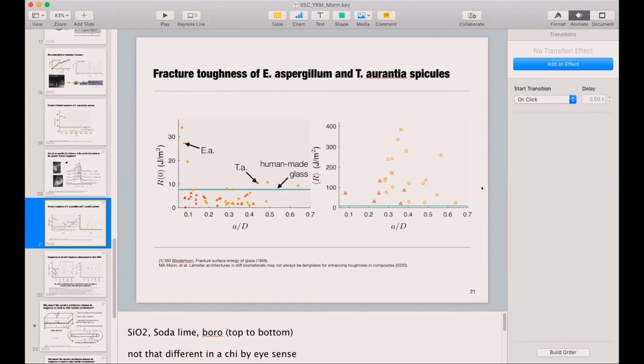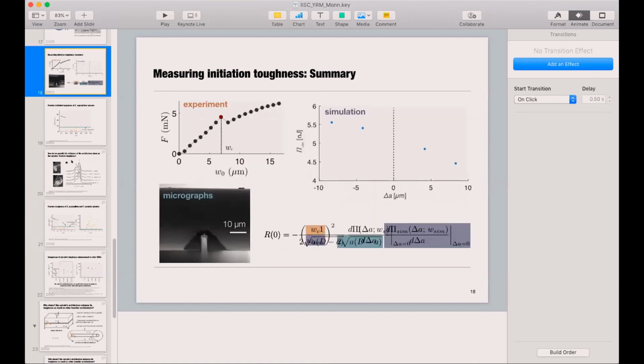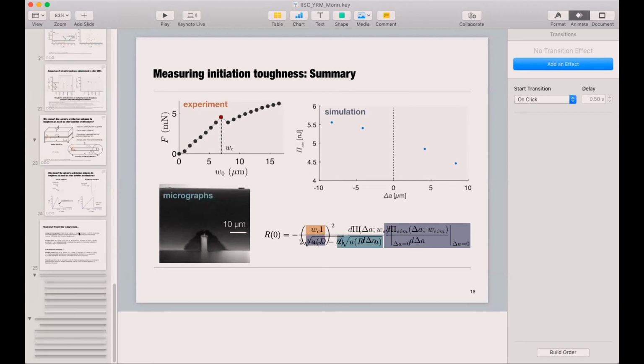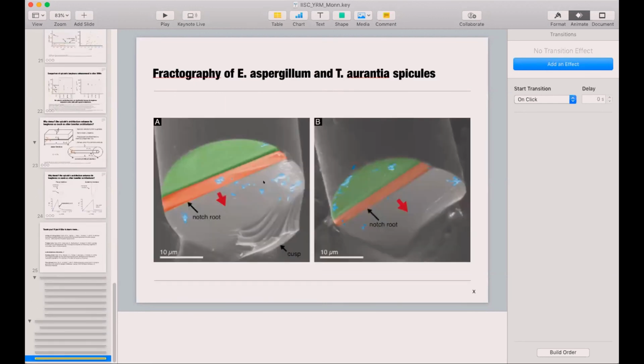Sure, yeah. I had another question about the experimental method itself. When you make these kinds of notches, since we also worked on clamped conditions, we always found that the notch was difficult to maintain straight. So when you make an assumption that it has a straight front of the notch in a certain section, that I guess is an assumption, right? So we imaged them after they failed. You can see a couple micrographs here where, again, the green is the macro notch and the orange is the micro notch, and you can actually see the notch root.